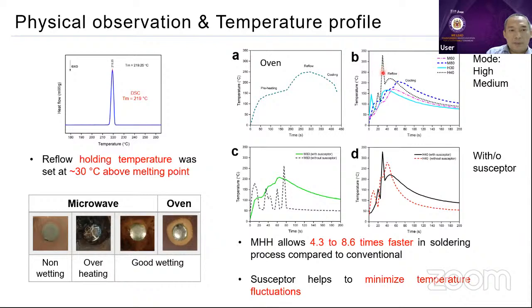This means that this setting, for example, high and 40 seconds of microwave, can reach this temperature, so this is a very good setting for the reflow. If you are using lower than that, for example medium, we cannot even reach 200 before it starts to cool down. So some of them are not good, right?